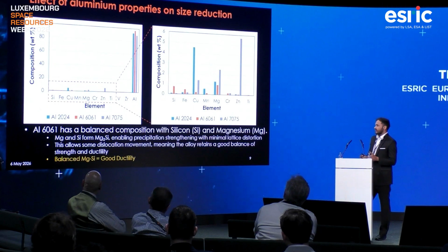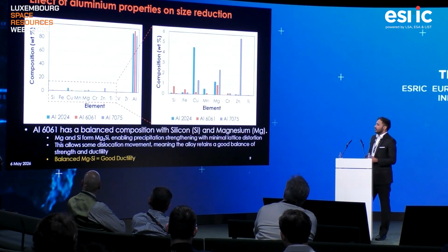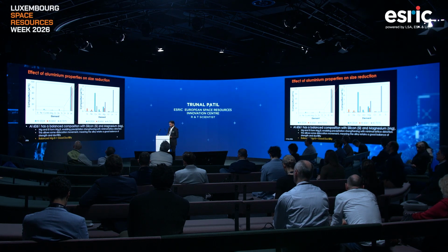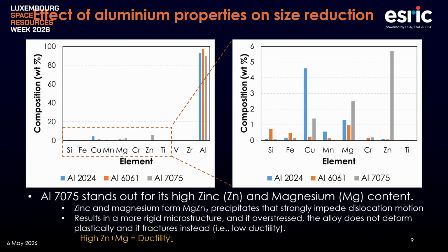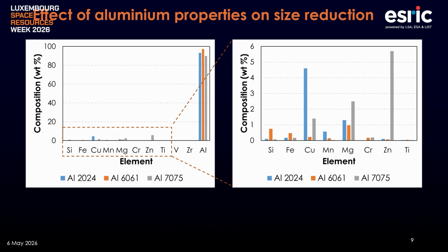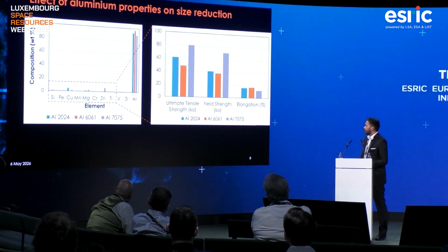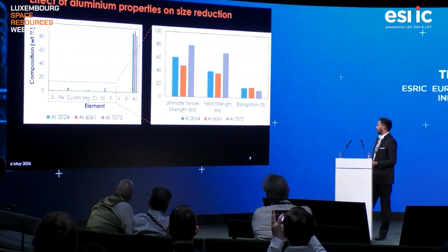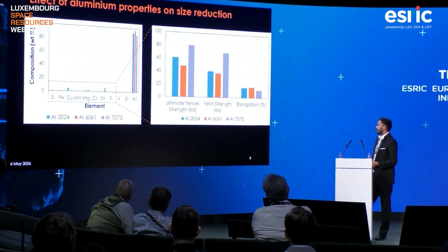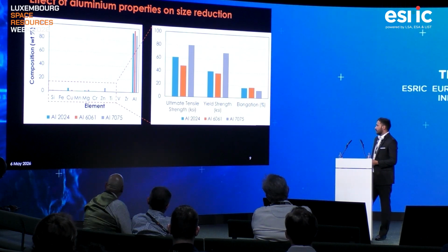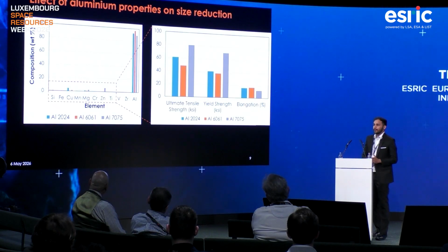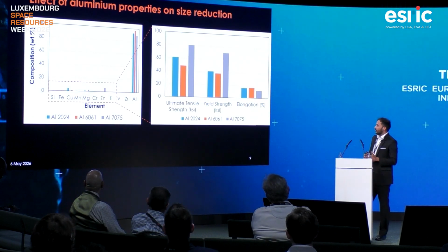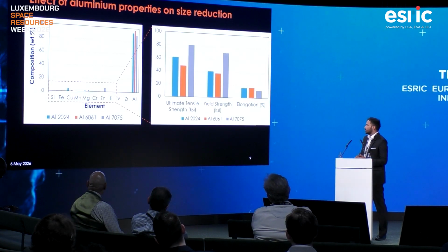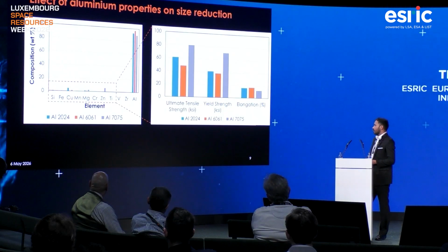So aluminum 6061, in this size reduction process, instead of fragmenting, deforms. In the case of aluminum 7075, it has high zinc and magnesium content, and because of that it's less ductile, so aluminum 7075 gets easily fragmented during this process. Also, with the material properties, we found that aluminum 6061 has a relatively higher elongation value, and that's why aluminum 6061 showed more jamming issues. So during the size reduction process, the performance depends on the material properties, and it varies with respect to each lunar hardware composition.